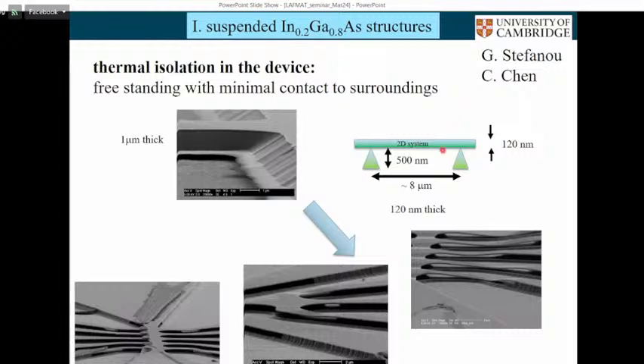We also discovered how large a structure we can make and keep it suspended. When you've got a 1 micron thick active layer, they're easy to suspend. You can suspend them over tens of microns. When we've got a structure that's 120 nanometers thick, we can suspend it over about 8 microns laterally. So these are some SEM images. They're obviously devices that have failed in some way. So this device here, you can see we've etched away underneath, but it's collapsed down. The active region where the two-dimensional electron gas is has collapsed down.